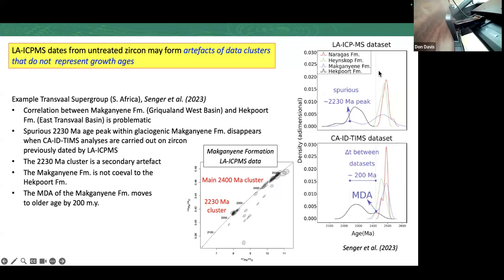Anyway, the other thing is laser ablation ICPMS. Of course, there's a huge difference between a lead over uranium age, which you have to use on Phanerozoic zircons, as you pointed out, and a lead-lead age, which you use on Precambrian rocks. There's no isotopic fractionation between the 207 and 206, so those ages should be much more accurate than ages based on 206 over 238. So you talked a lot about standards and stuff like that. But the problem with 206 over 238 is that the ratio isn't constant during the analysis. It goes up basically and sort of levels off the longer you analyze, over, say, a 30-second analysis. So exactly which value of 206 over 238 do you pick?